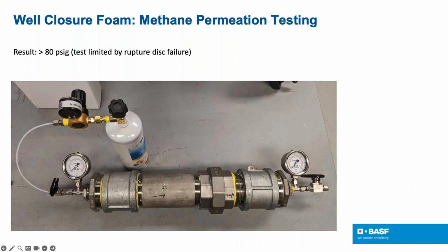So the next question we asked is, will the foam prevent methane leakage? Obviously, as Jonathan mentioned, abandoned wells leaking methane into the atmosphere is not helpful for our climate change goals. So we set up a simple test rig where we installed some polyurethane into a pipe to look for any methane permeation through the polyurethane. We saw no permeation up to 80 psi, which was the limit of the rig that we had in the lab, but some subsequent testing has shown success at much higher pressures as well. Next slide, please.